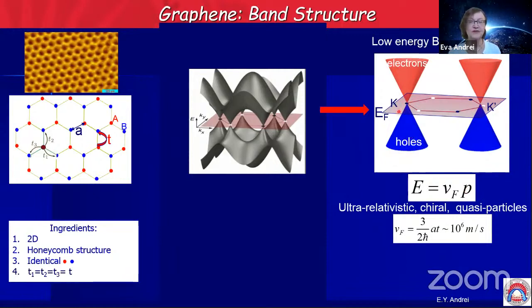The slope of the cones here is what we call the Fermi velocity, and it's purely determined by the lattice spacing A here and the hopping between adjacent atoms. So the Fermi velocity, which is equivalent to the speed of light if these were neutrinos or photons, is about 300 times smaller than the speed of light.